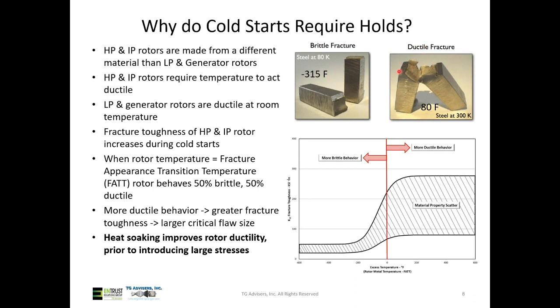To the contrary, here we have a ductile failure, which is 300 K now, which is approximately room temperature. What you can see is the crack could grow to a much more significant depth or size before we ultimately had this failure. So we call this a ductile failure. And when we are looking at rotors, we want them to exhibit ductile behavior because there's going to be flaws, there's going to be impurities in the rotor, and we want to make sure that it's not going to fail. So we want to allow for as large a crack as possible prior to failure.